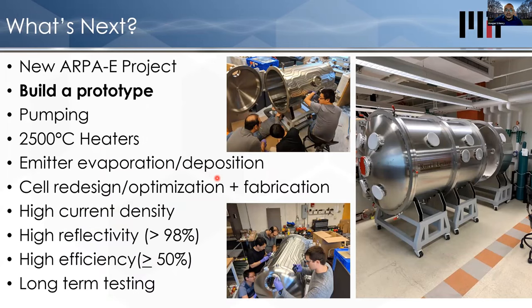We have a giant vacuum chamber that's 5 feet in diameter, 12 feet long. What I should say about this one key thing is this whole system's held in an inert environment. So you definitely can't get this hot with something like graphite in air. It will just burn. It'll oxidize. Instead, we keep it in a shell and keep it exposed to argon so that it won't have those interactions. And we've got a project with ARPA-E now demonstrating this at prototype scale.